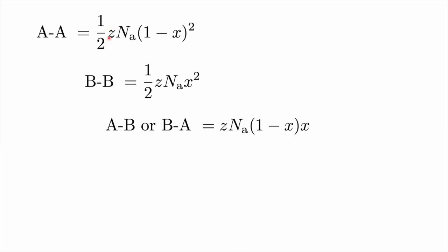So we define a coordination number Z. So for example, in a BCC lattice, the central atom would be surrounded by eight near neighbors. So the coordination number would be eight. So the chances of an AA pair are the probability of an A atom times the probability of finding another A atom times the coordination number, and then these terms which you are familiar with. And similarly, of BB bonds and of forming an AB bond and a BA bond by breaking this and this apart. So we have the numbers of these bonds.